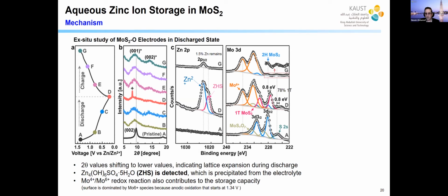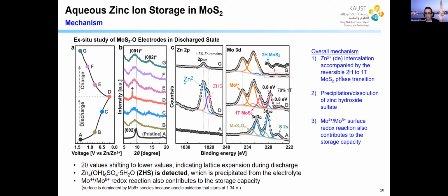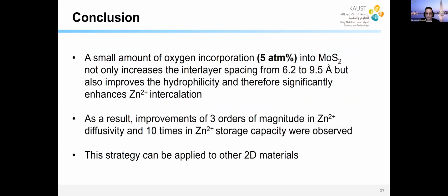The XPS is a little complicated, but it shows you the same story. Again, after intercalation, we have this 1T phase forming, and we have the change in oxidation state in moly oxide. And upon charge, you recover almost everything. So in summary, the mechanism here is a little complicated. Zinc intercalates into the cathode. This is accompanied by the transformation of molysulfide into 1T phase. There's a precipitation and dissolution of this zinc hydroxide byproduct. Luckily, on the cathode, this is a reversible process, but it may have a detrimental effect on rate performance. And then we have a change in the oxidation state. So this is all I want to say about this example.